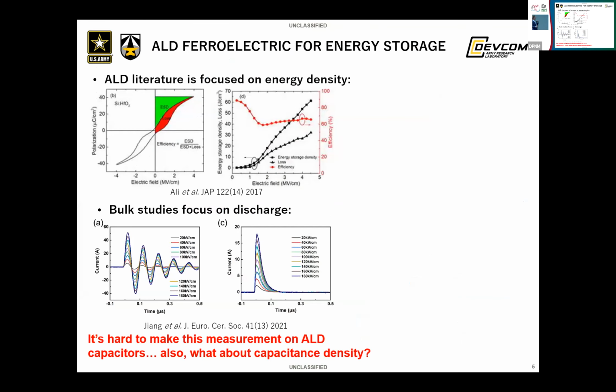So this is kind of the ubiquitous set of plots you see for an ALD ferroelectric energy storage paper. You have the hysteresis loop, and the area behind the loop is equivalent to the energy storage density. And then you can calculate the ratio of these areas, which gives you your density and your energy storage efficiency. But if you look at the literature on bulk pulsed power applications, everybody makes sure to include some actual ballistic discharge tests. And this is really hard to do with an ALD, a small capacitor. It just has a little amount of capacitance, and it's hard to set up that experiment.